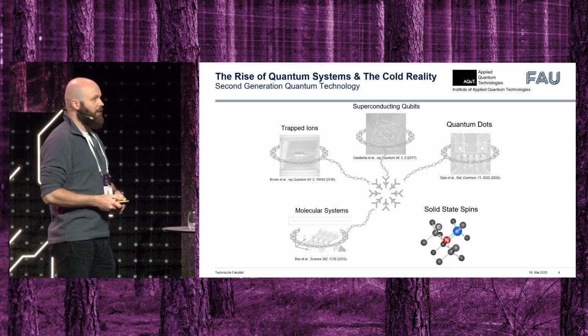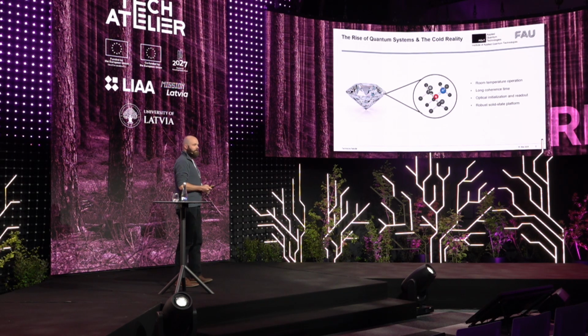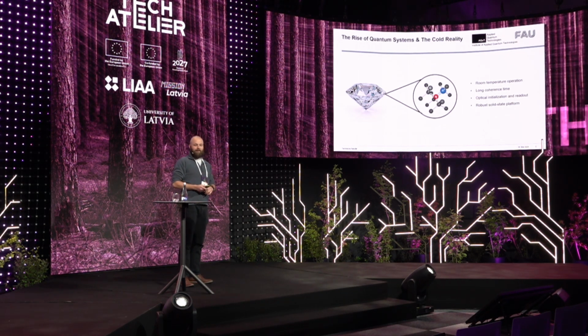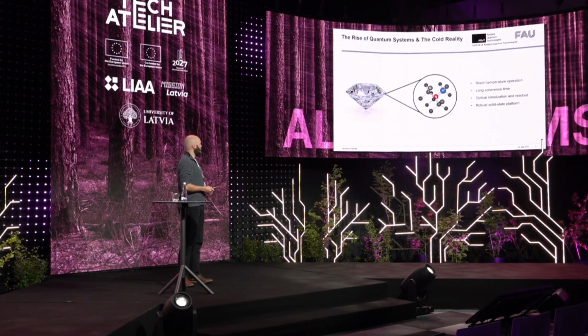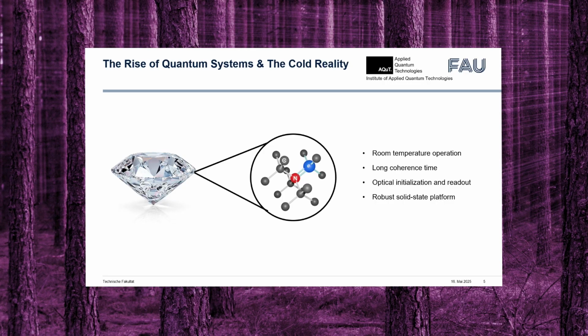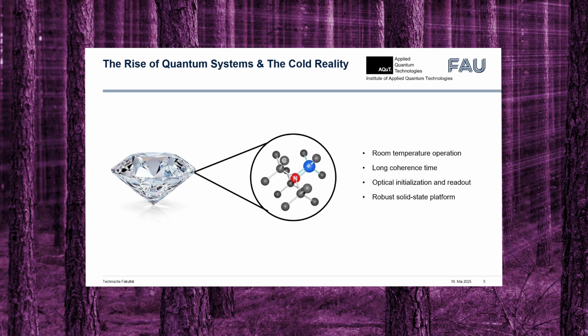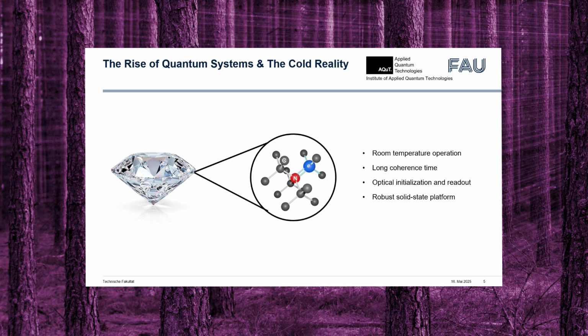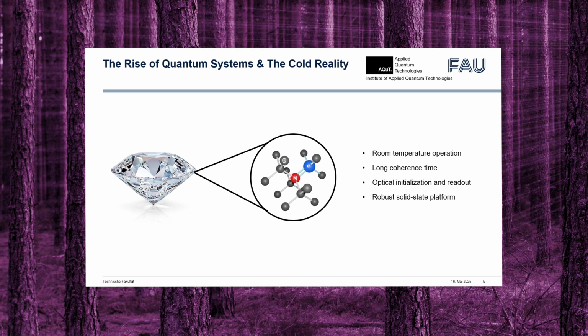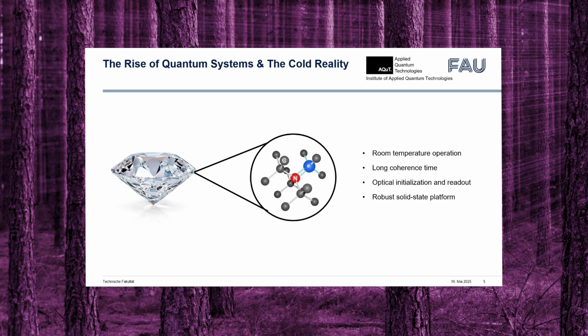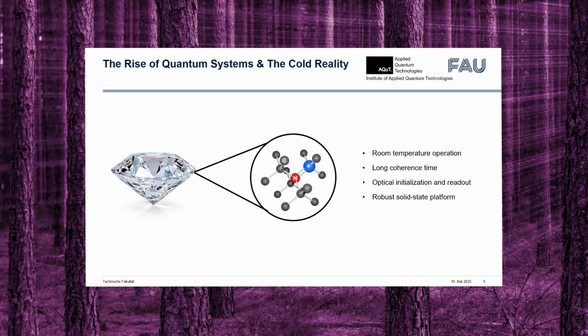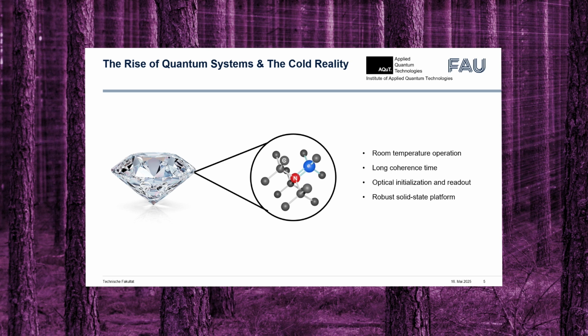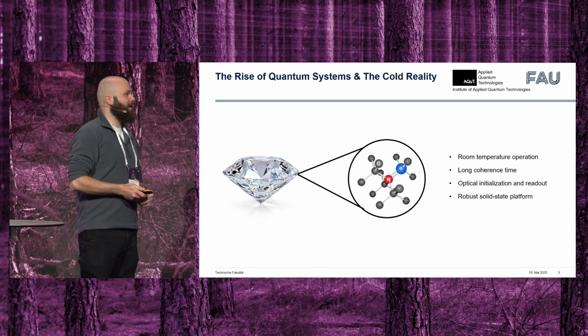And the poster child for the solid-state spin systems within the last 2 decades has been the nitrogen vacancy center. I'm sure if someone took a look at this field, you will have come across this big player. And the interesting thing is that it is literally just a substitutional nitrogen atom that is stuck within the carbon lattice and an adjacent vacancy that confines 2 unpaired electrons. And these 2 electrons make up our spin system. And this is what we refer to as a nitrogen vacancy center. And this is basically it. This is our sensor. Literally 2 missing carbon atoms within the lattice.